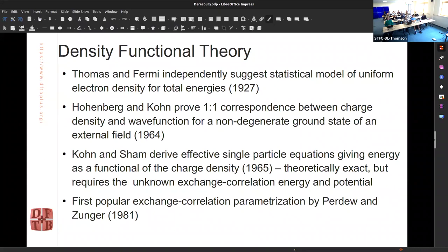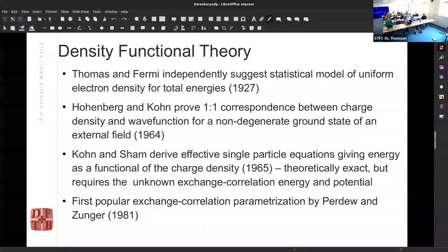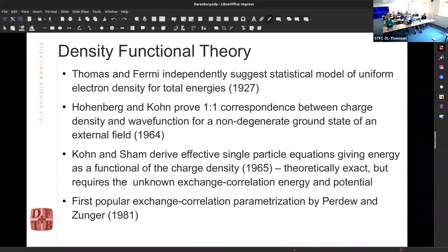The Hohenberg-Kohn proof of 1964 formally proves that the charge density encodes everything about the system. Unfortunately, the many-body physics is related to a term in that equation that we still don't know the exact answer to, and we've had 60 years of attempts to approximate that term. That was the main point of the 1965 paper by Walter Kohn — probably the large reason he got the Nobel Prize in 1998 — because the first practical schemes are the Kohn-Sham equations, where you write down a set of fictitious single-particle equations which give you your charge density and tell you everything about the system.